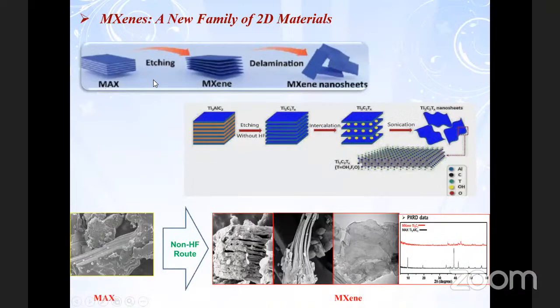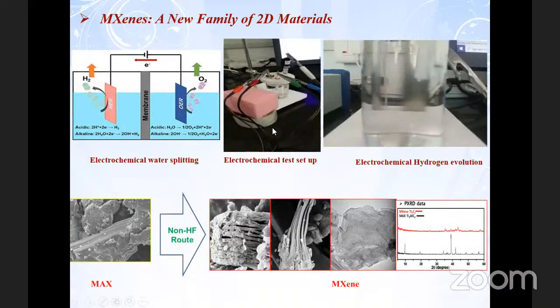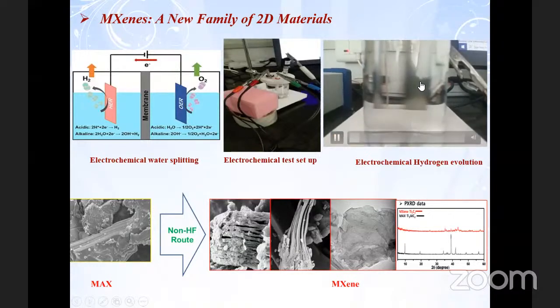So what we did, instead of using HF, we used many different non-HF routes, and our group has synthesized the material. We are working on using this material for hydrogen production, for electrochemical water splitting and the oxygen evolution reaction. I'll give you one example. This is the electrochemical setup where we are working on hydrogen production. Using this material, if you can see the video, I will show you. See, we were able to produce the hydrogen.